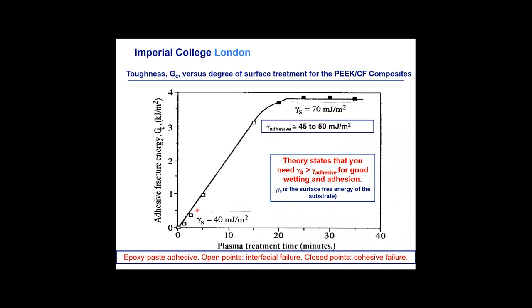Down here we obviously haven't met this criteria, and therefore we get poor wetting and adhesion, while up here we get the surface energy of the PEEK carbon fiber composite to be 70, greater than 45 to 50 of course, and therefore we get excellent wetting, very good adhesion, and we get cohesive failure through the adhesive layer itself. So the failure is in the glue, and that's why it plateaus out, and we have a toughness of about 4,000 joules per meter squared, which is very, very good indeed. So you can see the surface treatment is terribly effective for these thermoplastic fiber composites and is widely used now by industry.